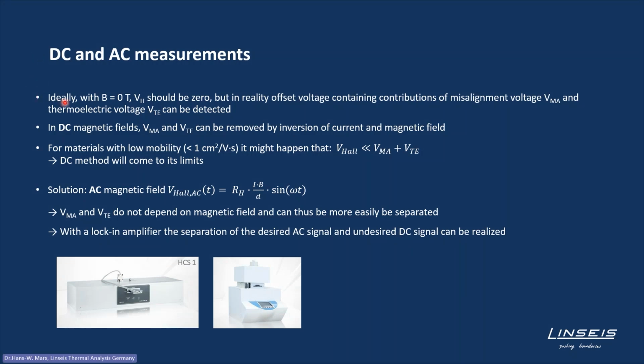In the ideal case, when you have no magnetic field, you should measure no Hall voltage. But in reality, sometimes there is an offset voltage, and this offset voltage contains contributions of the so-called misalignment voltage and the thermoelectric voltage. So in direct current magnetic fields or in the permanent magnet HCS1, the misalignment voltage and the thermoelectric voltage can be removed by inversion of the current and inversion of the magnetic field.